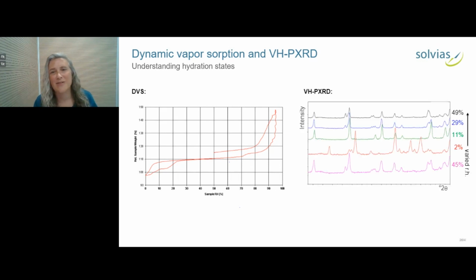And on the right-hand side, you see the variable humidity powder X-ray diffractograms. So we started at about 45% relative humidity. Then in the X-ray instrument, we lowered it to 2%, and that corresponds to here at the very lower left of the DVS. We found an anhydrous form that had not been previously discovered. Then if we raise the humidity to 11%, corresponding to this jump, this step in the DVS curve, we found a form that was designated as hydrate 1.